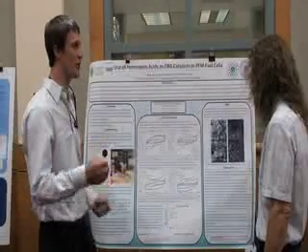So that's our glassy carbon electrode. That's a working electrode, and that's what creates that potential. And then our silver chloride is our reference electrode, and that's what reads the current coming through there. And then we have a platinum mesh, which is our auxiliary electrode, which absorbs and donates electrons for the solution. And then we just ran in a pH 2 buffer, so it's at acidic conditions. So it models what a fuel cell pH would be.